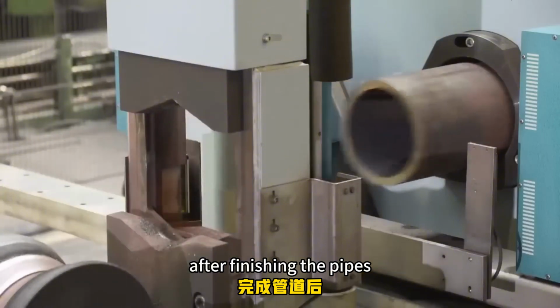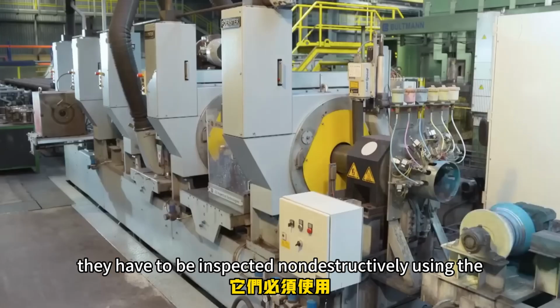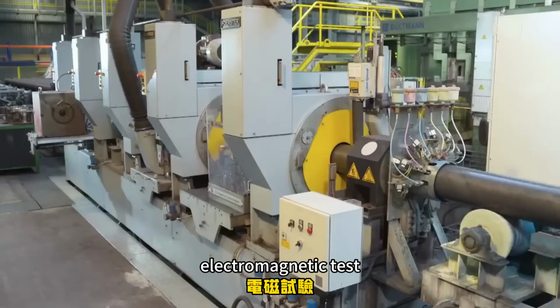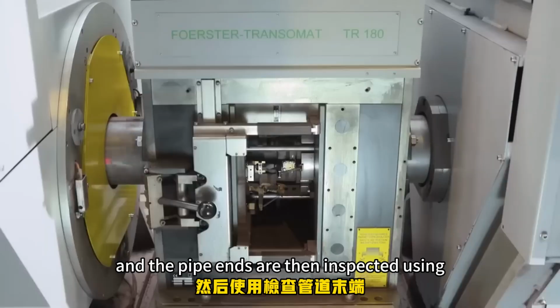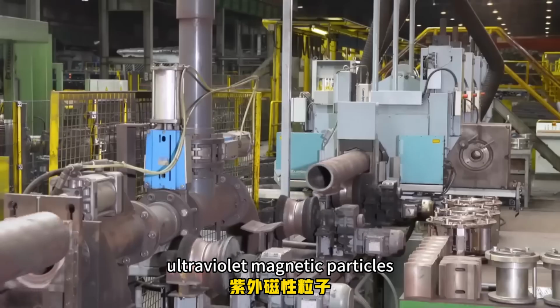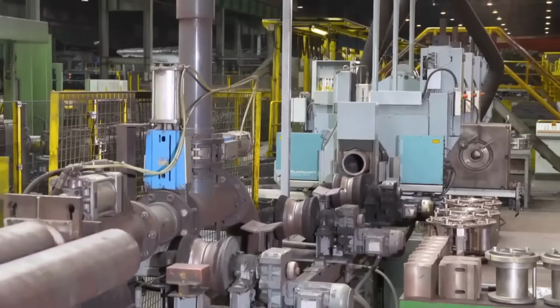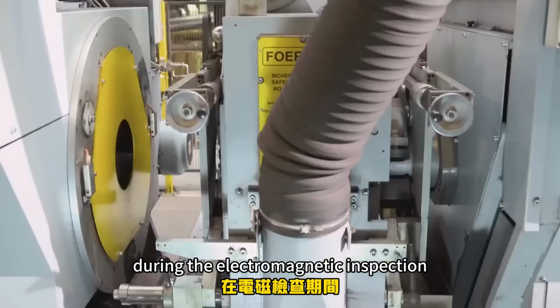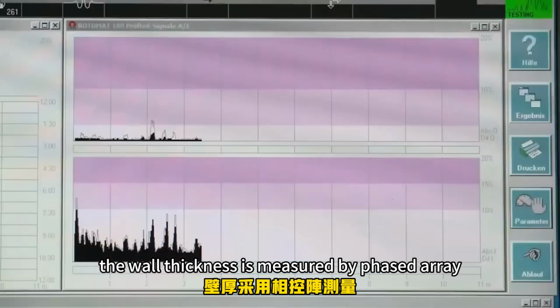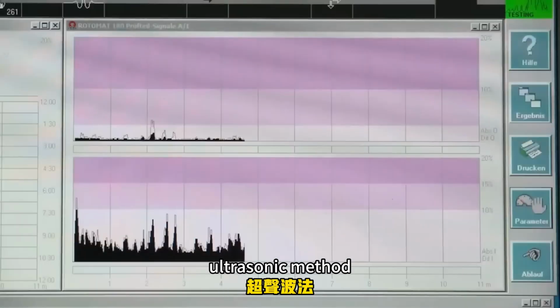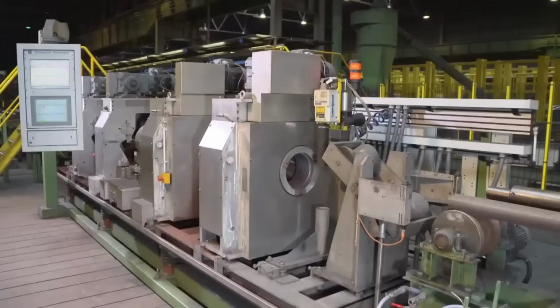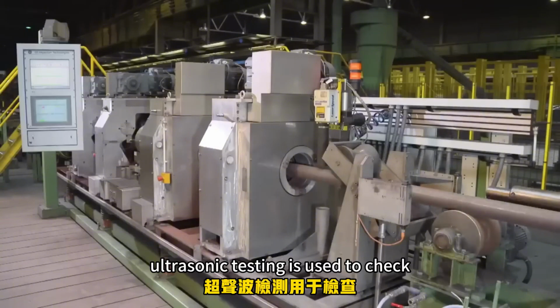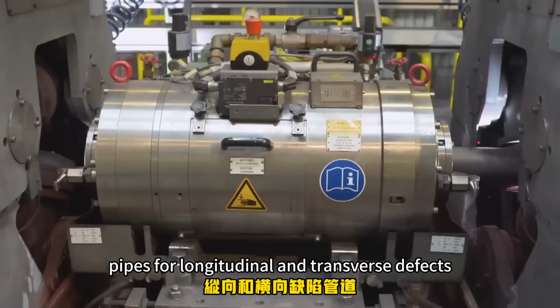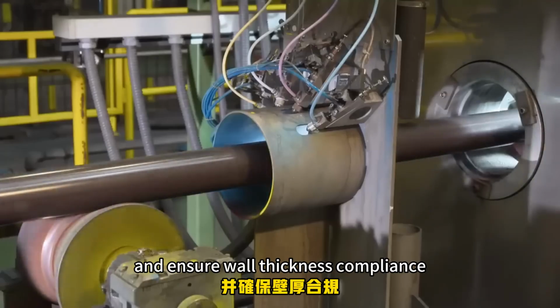After finishing the pipes, they have to be inspected non-destructively using the electromagnetic test, and the pipe ends are then inspected using ultraviolet magnetic particles. During the electromagnetic inspection, the wall thickness is measured by phased array ultrasonic method. Moreover, ultrasonic testing is used to check pipes for longitudinal and transverse defects and ensure wall thickness compliance.